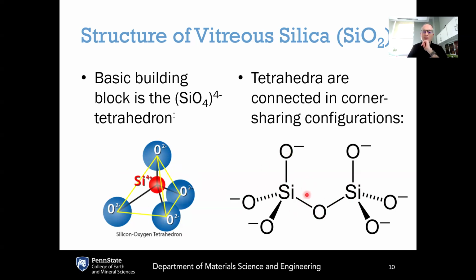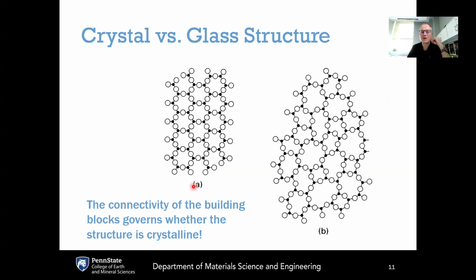These neighboring silica tetrahedra are connected to each other by sharing corners with each other. So this satisfies the third rule. And then at least 3 of the corners of the tetrahedra are shared. For pure silica, all 4 of the corners of the tetrahedra are shared. So the last rule is also satisfied. So we see here that silica satisfies all of Zachariasen's rules. And going back to this figure, this is actually Zachariasen's image of the glass structure on the right versus the crystal structure on the left.